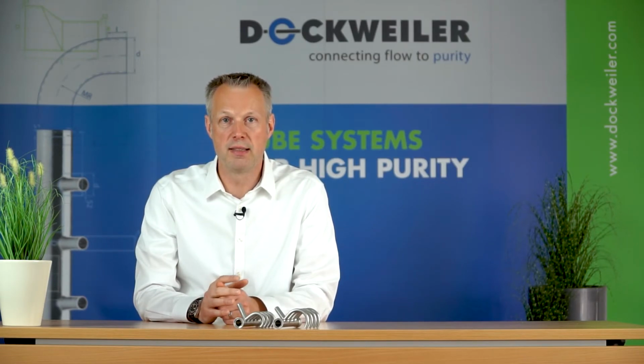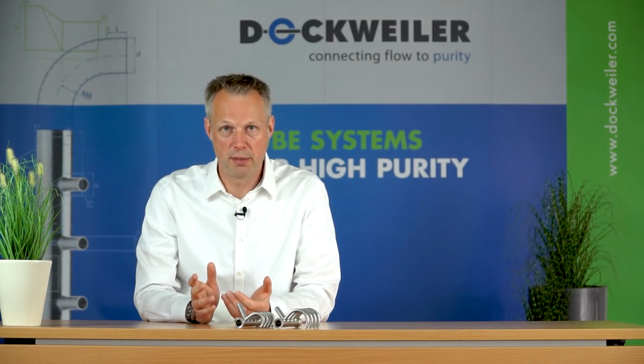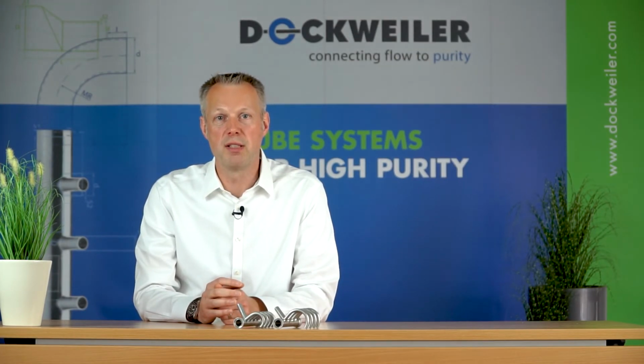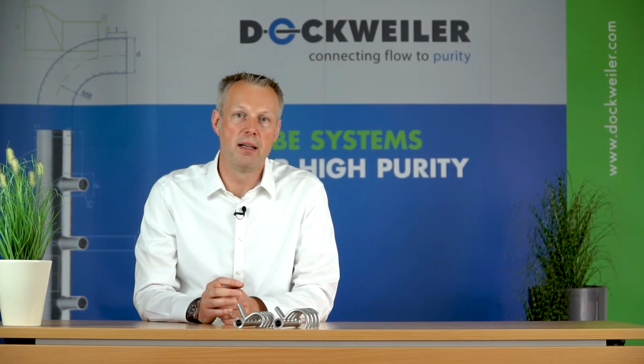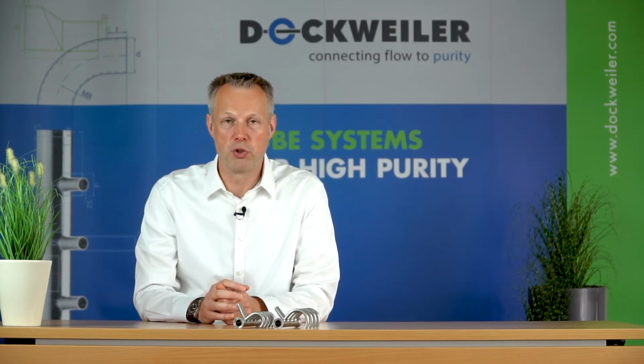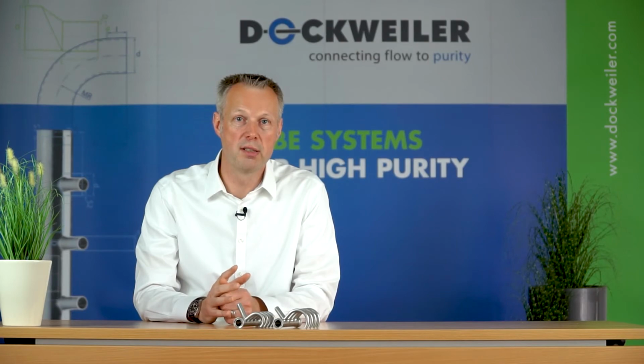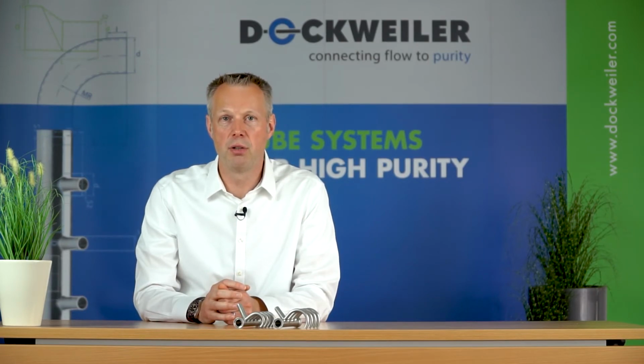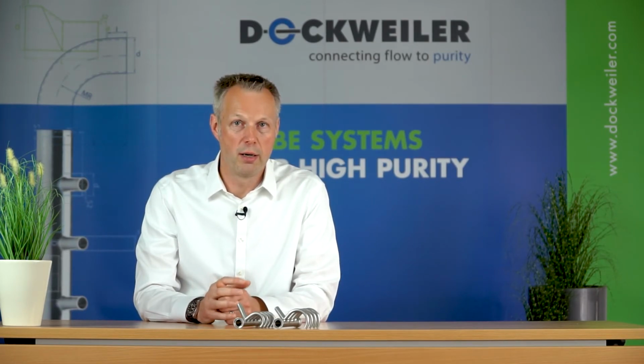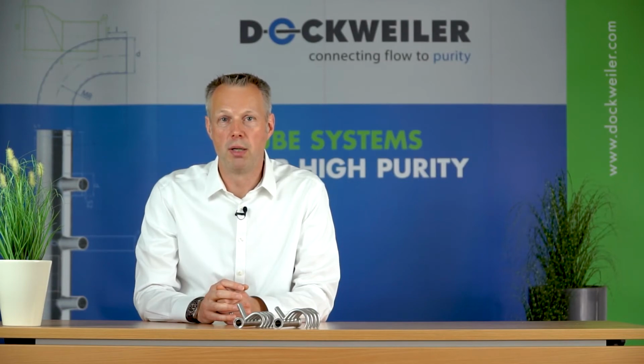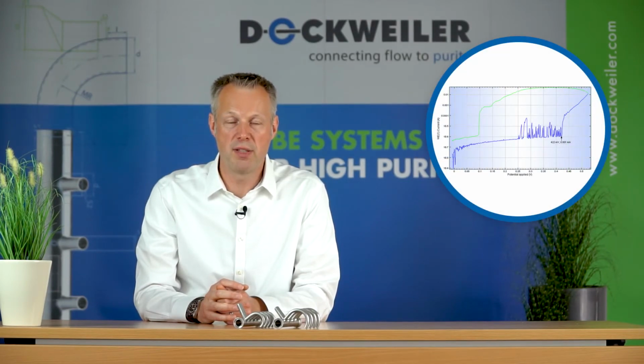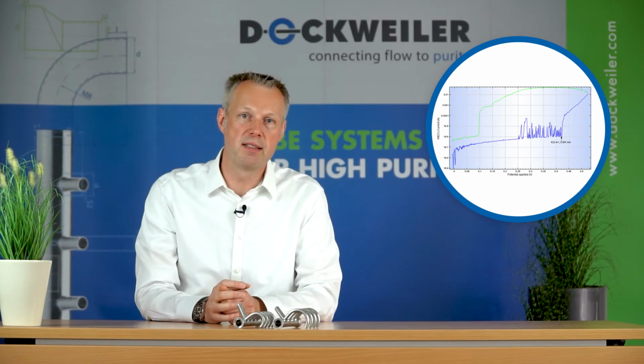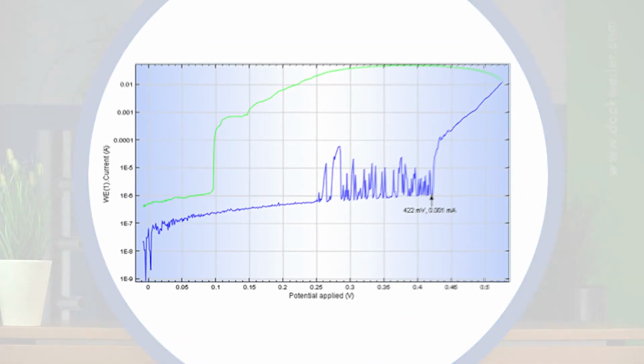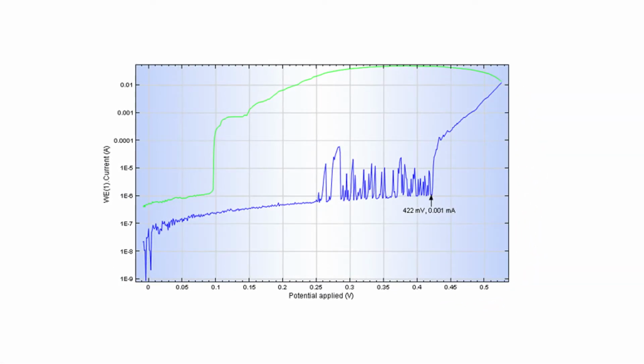What you're doing is you increase the voltage, you increase the potential, and the result is a flow of current, which is certainly initially small, but the higher you crank up the potential, the more current will flow. This will end up, as you can see up here, in a kind of jitter, a kind of noise that you will see here.